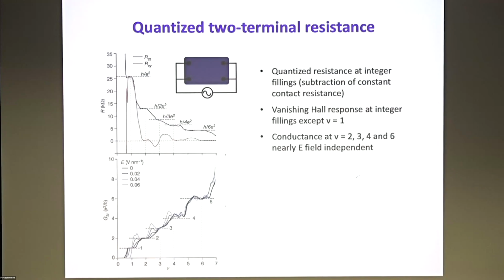And this is a plot of the two-terminal conductance, which is 1 over the two-terminal resistance, as a function of filling factor at different electric fields. You can see some clear steps of 1, 2, 3, 4, 6 in units of e squared over h. I want to note that for the incompressible region, the conductance is independent of the electric field. But for the compressible region in between, the two-terminal conductance is dependent on the electric field that we apply to the sample.